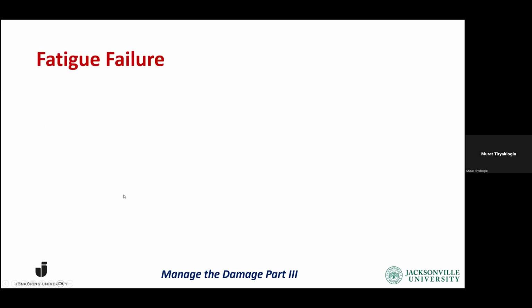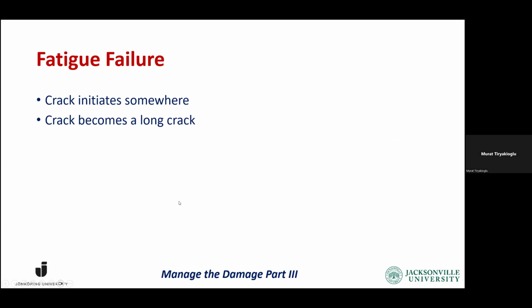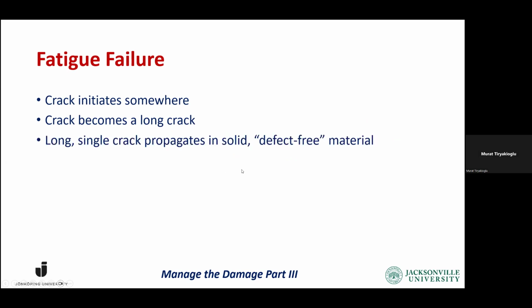Okay, so fatigue failure is, as we learn in metallurgy books or mechanical engineering books, we have all been taught that a crack initiates somewhere. It can be from a design flaw, it can be from a defect, or it can be from some sort of stress concentration. Then the crack becomes a long crack. And the long single crack propagates in solid, defect-free material. That has been the thinking. So one single crack propagates until the final fracture occurs at the critical crack length. That's what we've all been taught.